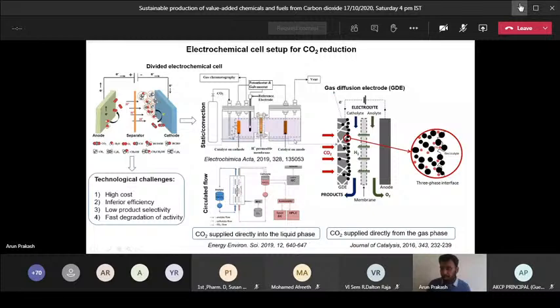Always, when you have a higher Tafel slope value, it means the kinetics is poor, and a different mechanism may also occur. If the Tafel slope is lower, like 115 millivolts, close to 120 millivolts, the kinetics is much more favored.